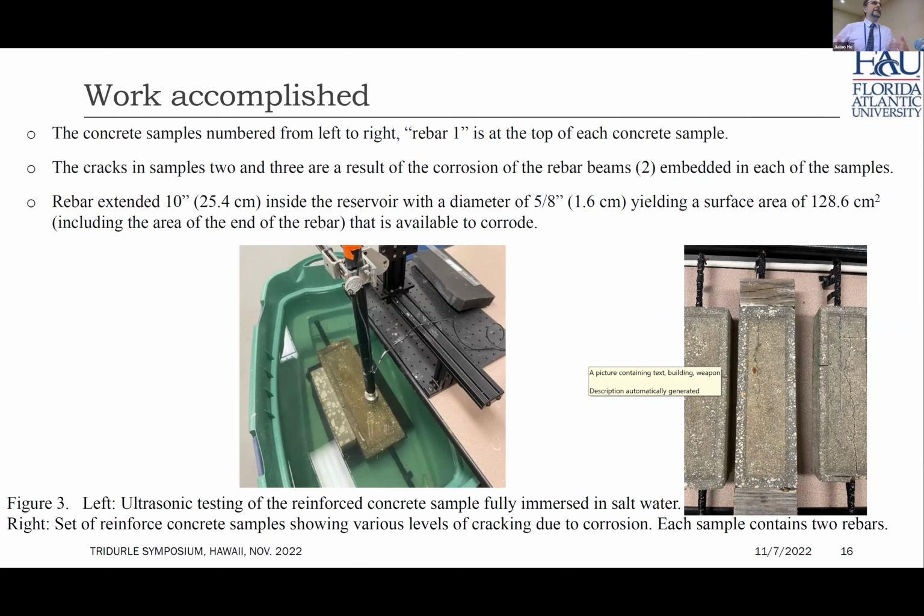And we repeated tests again and again, allowing for further corrosion using salty water over the course of about 8 months. And you can actually see the setup over here. It's very simple. We place as accurately as we can the transducer over the rebar, and we scan the rebar, and all the characteristics of the concrete sample is shown here, with the understanding that when we number the samples, sample 1 is the one with no sign of cracks, sample 3 is the one with a lot of cracks from left to right, and there are 2 rebars in each of the samples, which we monitor, a top and